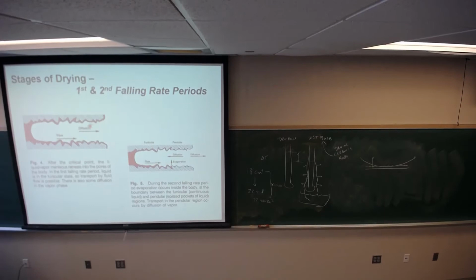This way, water saturates the pore structure and the pore walls, and then it works its way out and forms a film on the surface. Then you get free evaporation from the surface. So you get flow of water along the pore structure. When you get below a certain water content, this shuts off. That flow stops. Once that flow stops, there's no more movement of water to the surface as liquid water. Now it's all diffusion related, evaporation diffusion, and that's an extremely slow process.